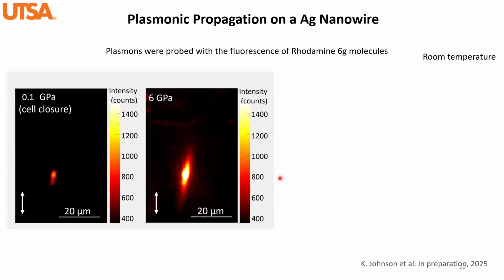In this slide, I'm showing a comparison of plasmon propagation on a silver nanowire at low pressure, when the cell was just closed, and at a higher pressure of 6 gigapascals. As I mentioned, plasmons were probed with the fluorescence of rhodamine 6G molecules. All light emission you see is emission from the dye. This experiment was carried out at room temperature, so there are no temperature effects; things are pretty simple, only pressure effects here. As you can see, we saw a significantly longer propagation distance under high pressure, and we tried to quantify that.